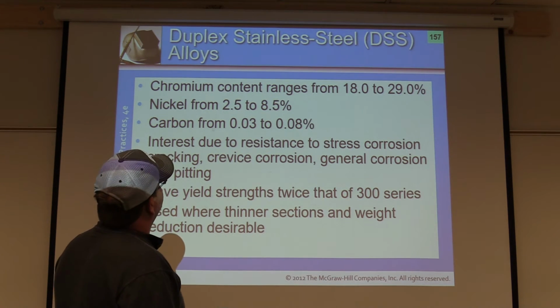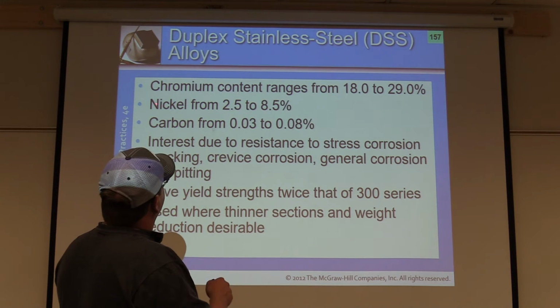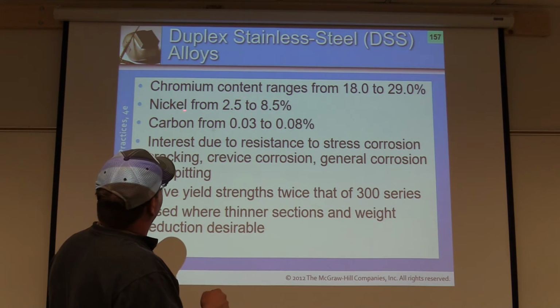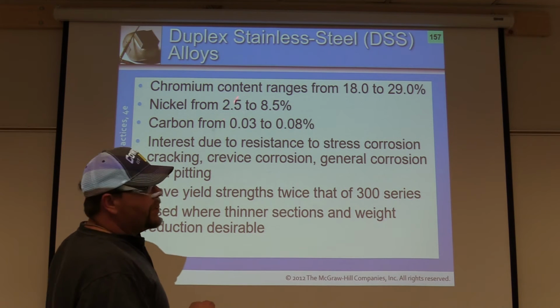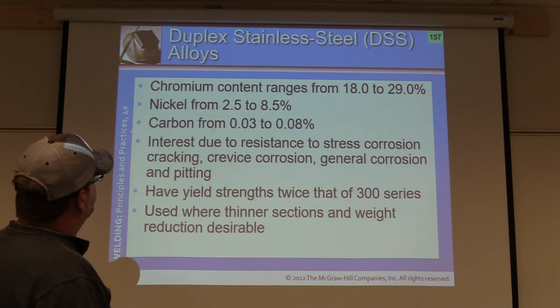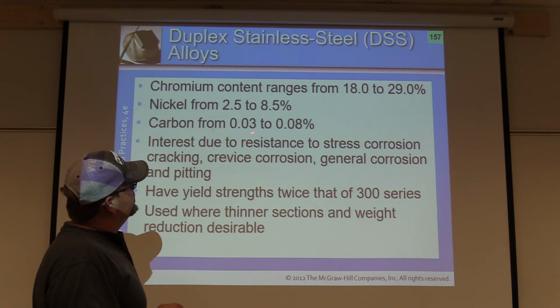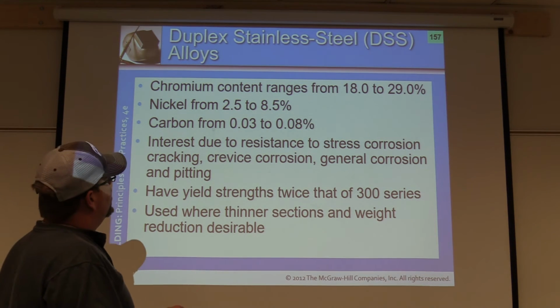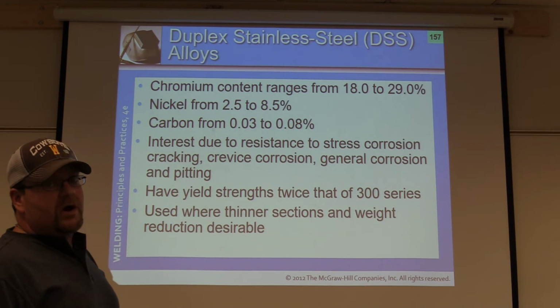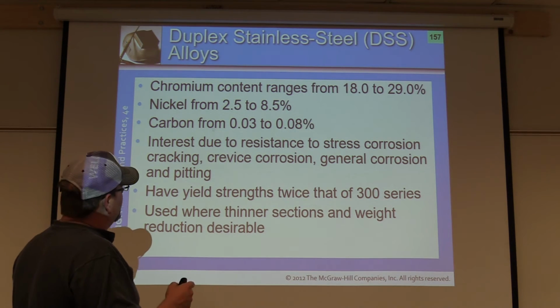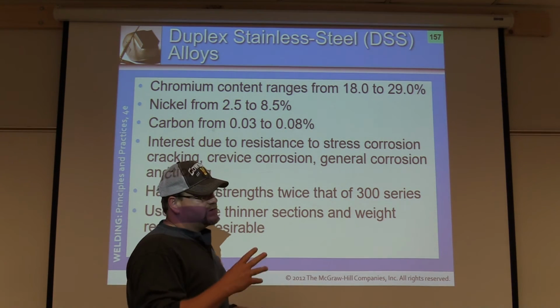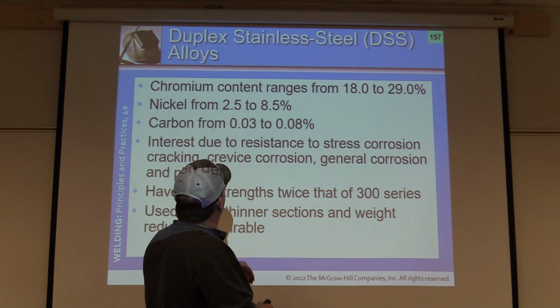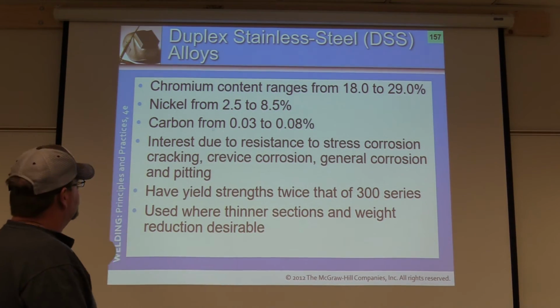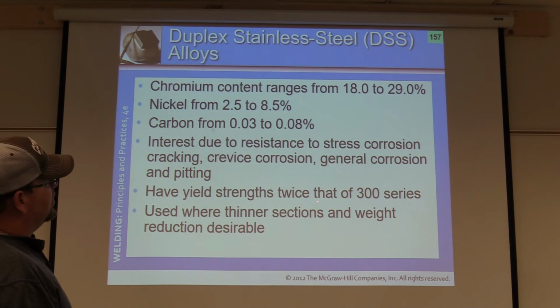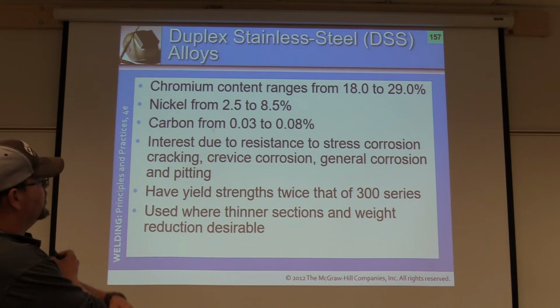Okay, duplex grade stainless steels. Nickel's not quite as high as the 200 to 300 series. Carbon's even lower yet though. Okay, so a lot of times you're seeing a chemical process come through, like in a piping system, or maybe a chute system, to where it'll wear out right next to the weld pattern. We get the sensitization along the weld toe. This might be the greatest stainless steel that we'd want to use. It has twice the yield strength of the 300 series.